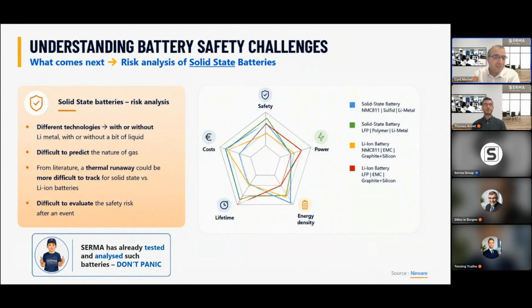Which means that it's more and more difficult to track it in the system, because the solid does not have the same thermal ability to propagate the heat as the liquid. And this will, of course, be more difficult to track. And also, again, at SERMA, we have already tested such technologies, and we also try to adapt our way of measuring for this kind of battery.